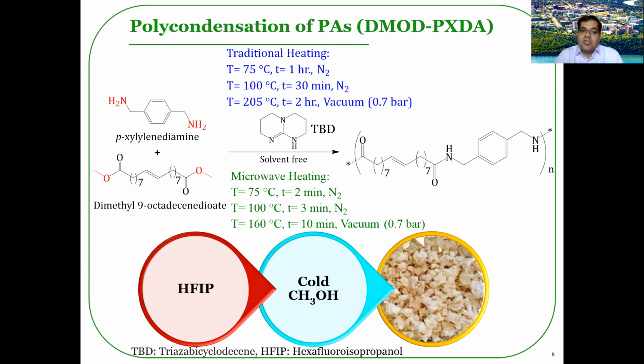Although the traditional polycondensation of monomers was completed after 3.5 hours reaction process at the final temperature of 205 degrees centigrade under vacuum, the microwave polycondensation of monomers was completed just after 15 minutes at the final temperature of 160 degrees centigrade under vacuum. Unfortunately, monomers couldn't tolerate more than 160 degrees centigrade under microwave irradiation. It could be potentially due to the decomposition of monomers under microwave irradiation at higher temperatures.